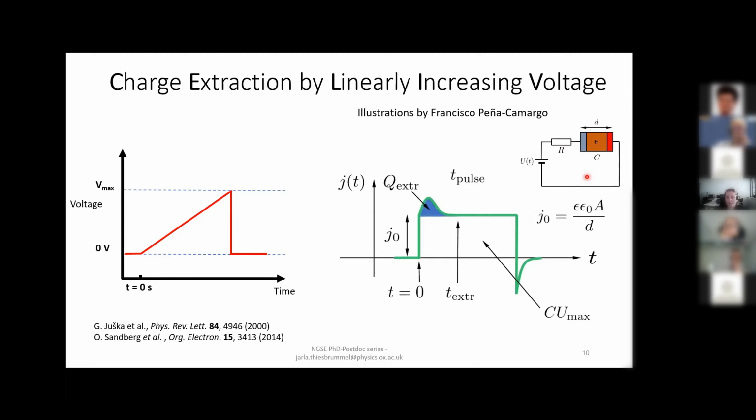And that is what makes this technique so powerful, because if you see the charge in the CELIV measurement, then it's relevant for the device performance. Whereas if you don't see it, that means that the concentration is below the capacitive charge, and we've done some simulations that show that then it's likely not relevant for the device performance. All right, so that is how CELIV measurements work. If you want to read more, I would recommend these two references, one about CELIV in general and one about how CELIV can be used to quantify doping.